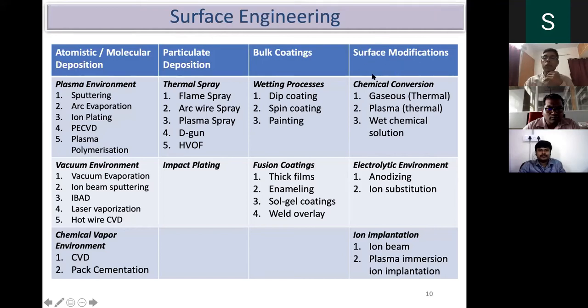And in surface modification, you modify only the surface. For example, ion implantation and plasma ion implantation, you just bombard, and that will go only a few nanometers, like up to 100 or at the maximum 200 or something like that. It will go and it will stop there. And if you heat them, the collision cascade around that area will create a few nanoparticles, or maybe new phases you can form at the top layer, the very top layer.